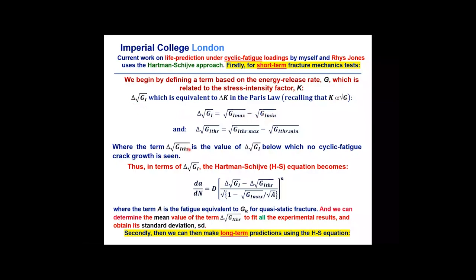We can also define a threshold term. Now, delta root G threshold is the value of the energy release rate, this term, below which no cyclic fatigue crack growth is seen. So it gives us a lower limit to the point at which we see cyclic fatigue crack growth. Now, we've expressed this and embodied it into what's known as the Hartman-Schijve equation. That's this equation. And this equation relates the rate of crack growth to constants D and n. A is the fatigue equivalent of the fracture energy. So we can relate the rate of crack growth per cycle, da/dN, to our energy release rate range here.